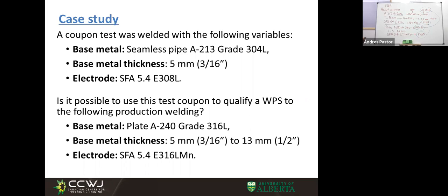Okay? So the problem is in the thickness of the base metal. Okay? In this production weld, the thickness is between 5 millimeters and 13 millimeters. And the qualified range, according to these actual variables, is from 1.5 millimeters to 10 millimeters. Okay? So I have a range out of the qualified range. Okay? So here I have a problem. So this is an essential variable. So I have to qualify a new welding procedure, okay, to cover these variables. Okay, this is the concept.